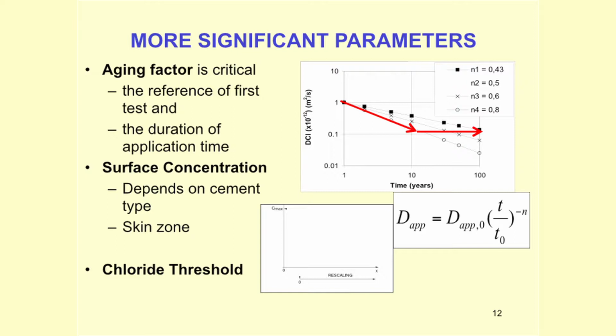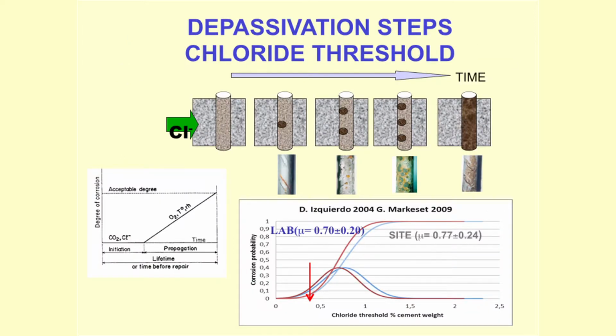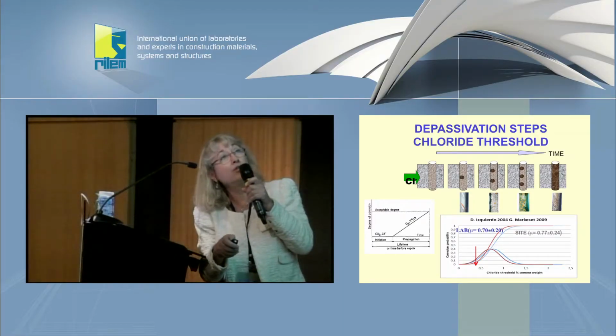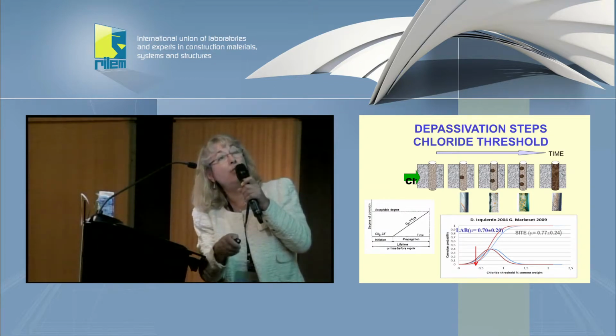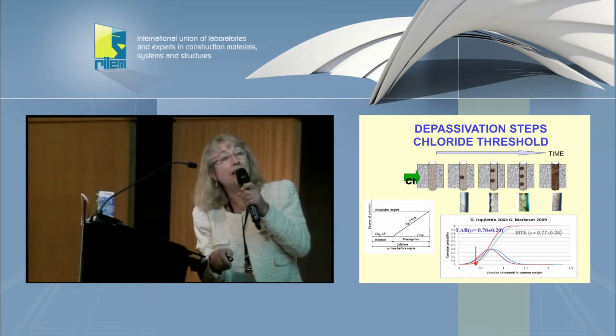And of course, about the chloride threshold is also important, as this is one of the discussions, which is the chloride threshold. First, we should imagine, as I have presented previously, the depassivation not as just a point, but as a continuous evolution in which the area affected, if it is carbonation, will be the external part, the area affected around the perimeter will increase with time. In that case, the amount of damage will increase with time. In that case, the depassivation is like a period of time, and the chloride threshold in that case is also a kind of statistical distribution.